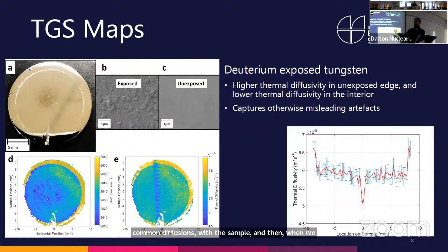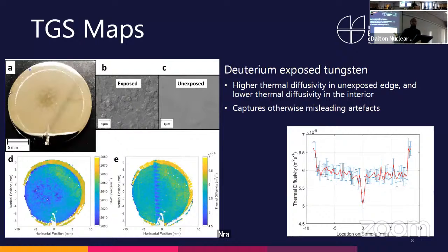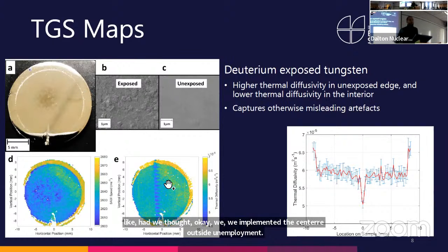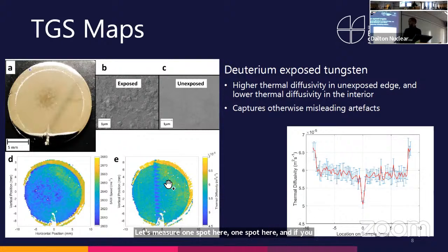And then when we showed this map to the guy who gave us the sample, he was like, oh yeah, that reminds me, we did NRA, nuclear reaction analysis. They had done some NRA measurements, which involved implanting your sample with helium ions or hydrogen, I think helium ions. So this was an effect of the NRA measurement that we picked up in our line scan. Had we thought, okay, we implanted the center, the outside's unimplanted, let's measure one spot here, one spot here, and if you had selected one of these spots, you would be coming to wrong conclusions. So that shows one of the benefits of doing a 2D map.